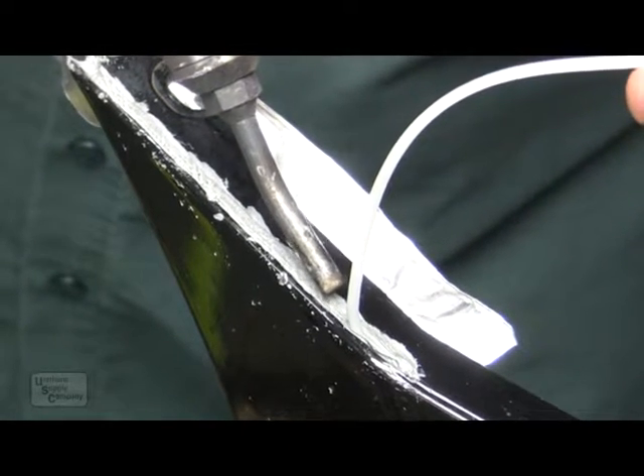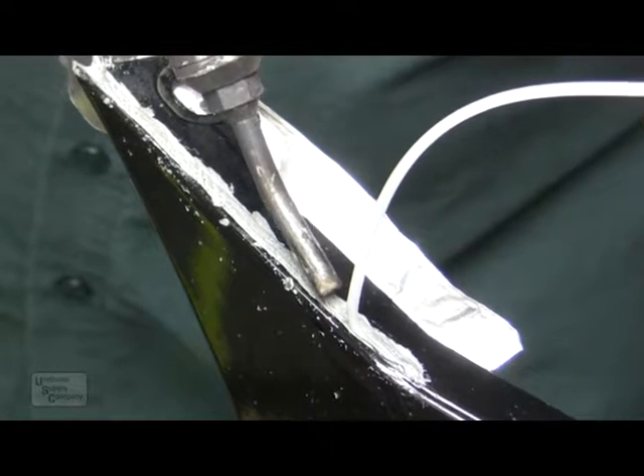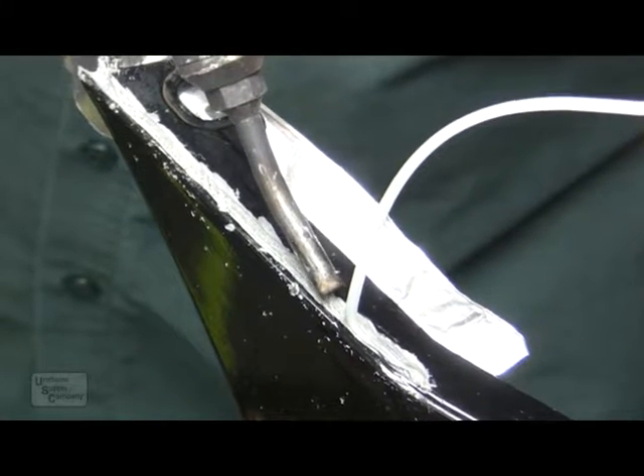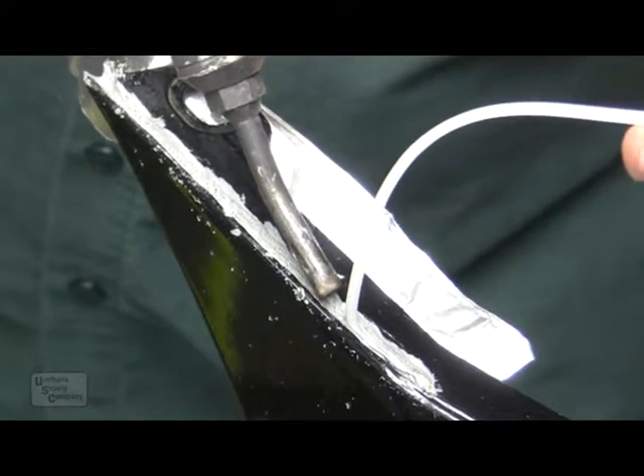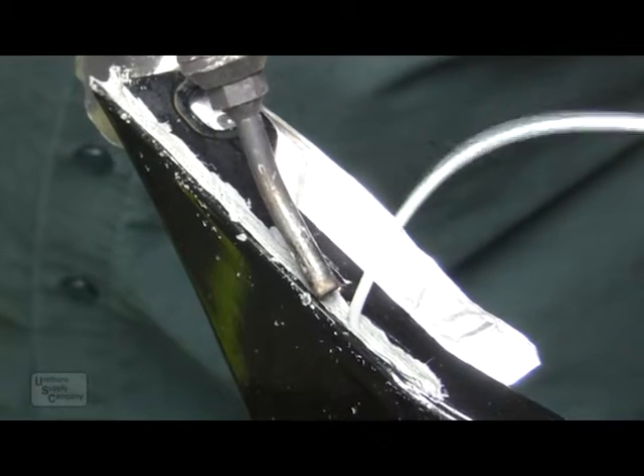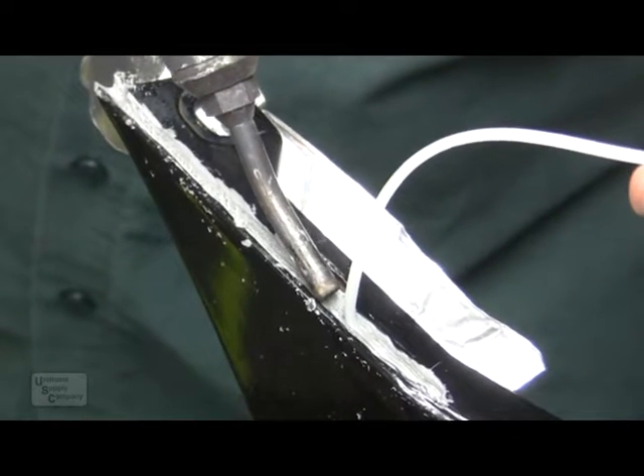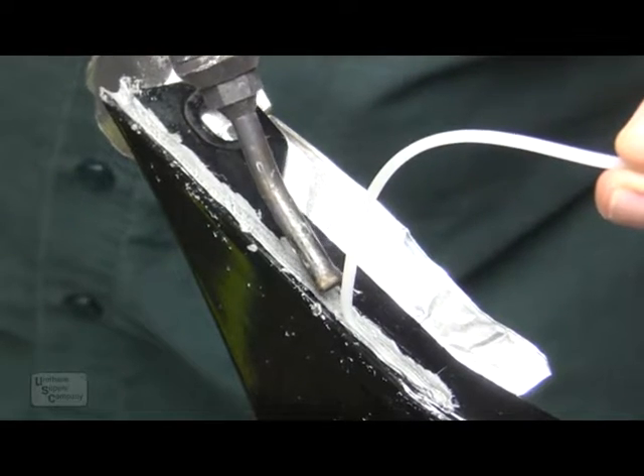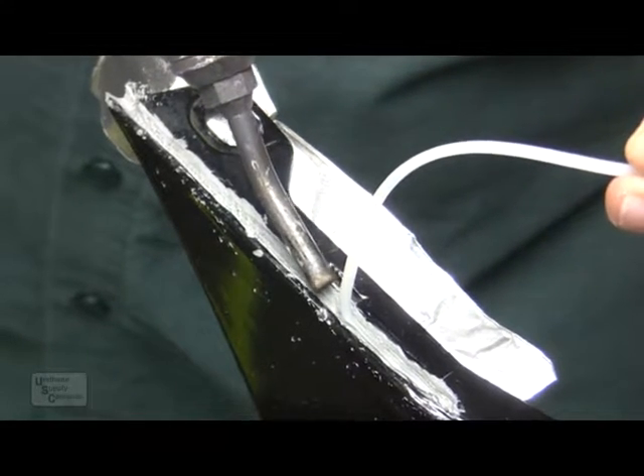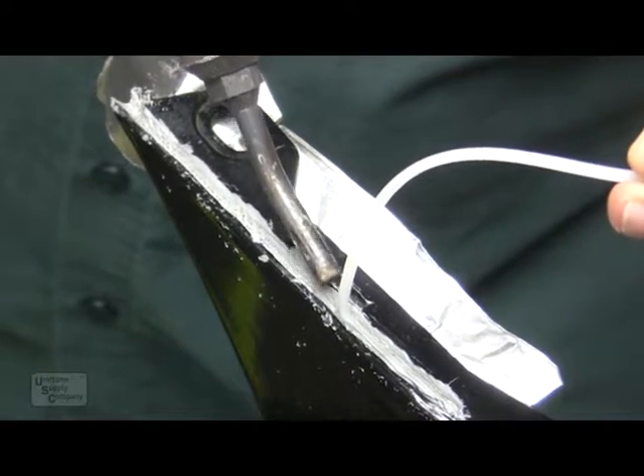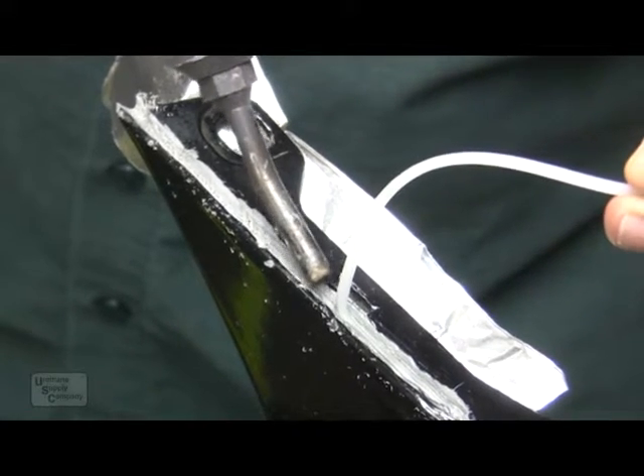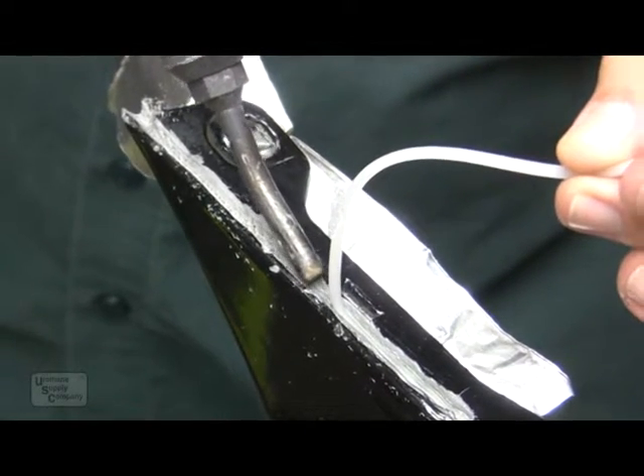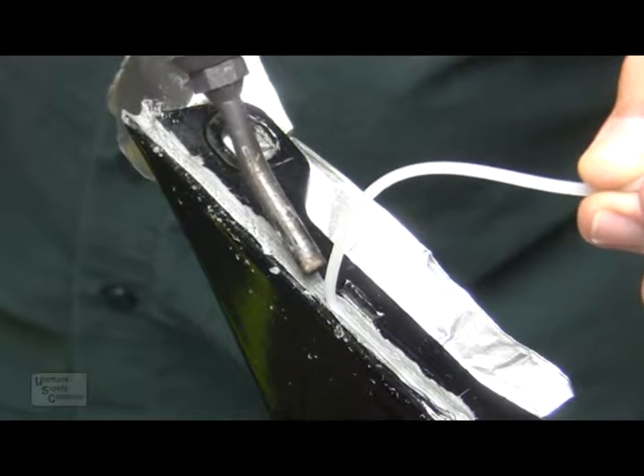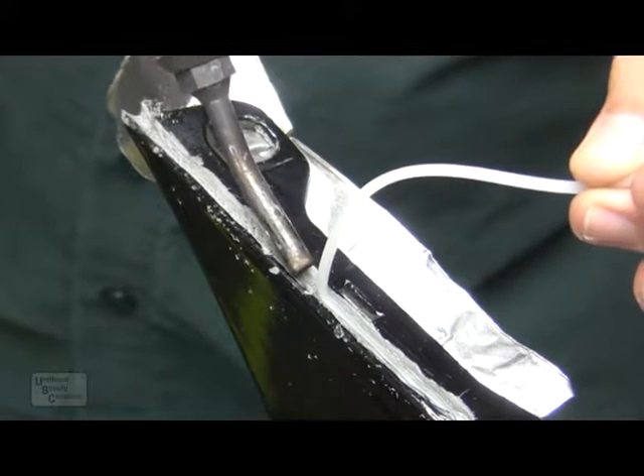For repairs on thin areas like this, the nitrogen flow is turned way down to about 7 liters per minute. Notice how the torch is focusing most of the heat on the rod instead of the bumper. This is because the bumper is so thin in this area, especially where it's been V-grooved. You want to melt the surface of the bumper, but you don't want to overheat the base material.